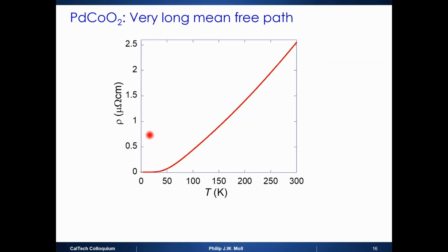Here, you see its in-plane resistivity starts out at a few micro-ohm centimeters at room temperature. So it's almost as good. Now, copper is more conductive, but it also has three times more electrons, so its mean free path is already better than copper. And then at low temperatures, you end up with something like 5 to 6 nano-ohm centimeters. So this is really a very, very clean metal. Because of that and its lower carrier density, you end up with very long mean free paths, 20, 25 microns. And it's a very pure material. Everything you take out of the oven, there's no magic, no 30 years of materials optimization. You just throw it into the oven, you pick out the crystal, and it will have at least 20 microns of mean free path. It's actually hard to disorder, but that's a separate story.